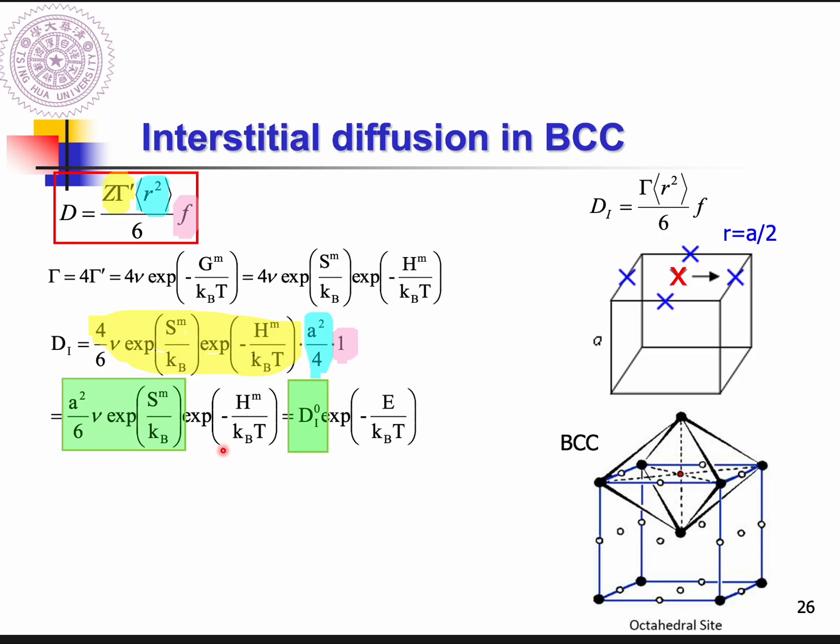Okay, so now we have successfully formulated the diffusivity of this solute atom located at the interstitial site. I want to explain more about a question some students ask me: Professor, can this solute atom at this octahedral interstitial site jump to here, instead of jumping here? If you calculate the distance between these two interstitial sites, this is longer than this distance, right? Don't forget, when you determine the jump distance, direction, and also the distance